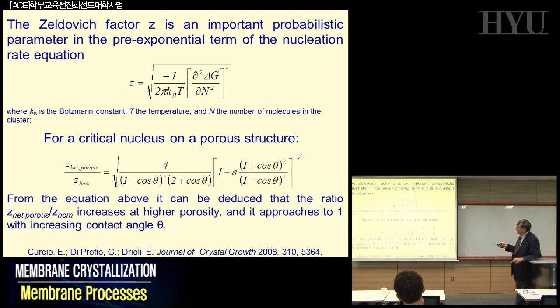So this is the term that Zeldovich was introducing. What's interesting is that this term can now be modified, utilizing the delta G that we calculate for this porous material, introducing this porosity factor epsilon, etc. And so you can have at the end a Zeldovich factor for the heterogeneous porous material and the homogeneous system. And that is the equation that you have.